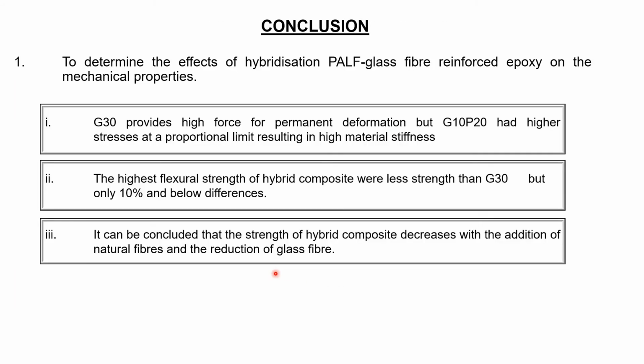The last one is conclusion. Conclusion for objective 1: G30 provides high force for permanent deformation, but G10P20 had higher stresses at the proportional limit, resulting in high material stiffness. The highest flexural strength of hybrid composite was less than G30, but with only 10% and below difference. It can be concluded that the strength of hybrid composite decreases with the addition of natural fiber and reduction of glass fiber.